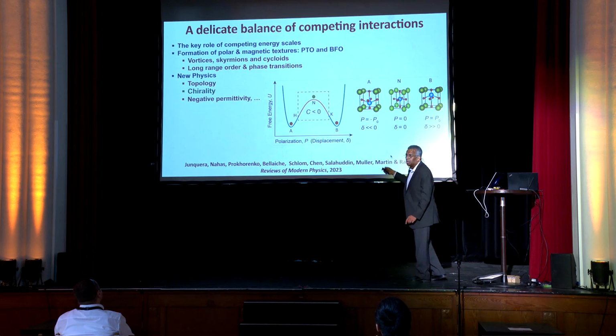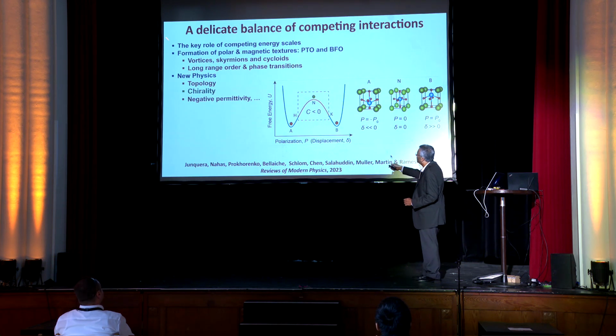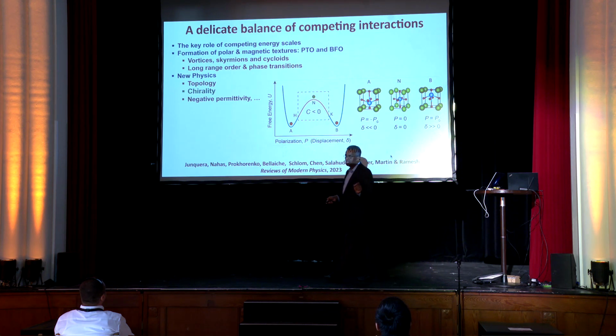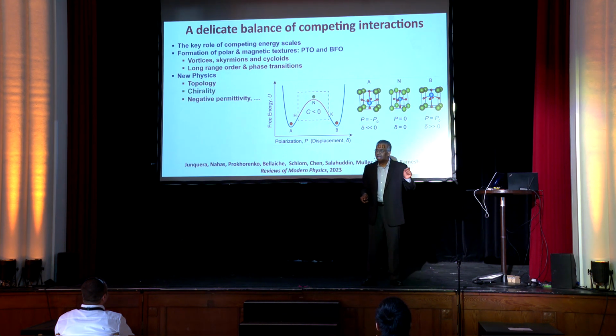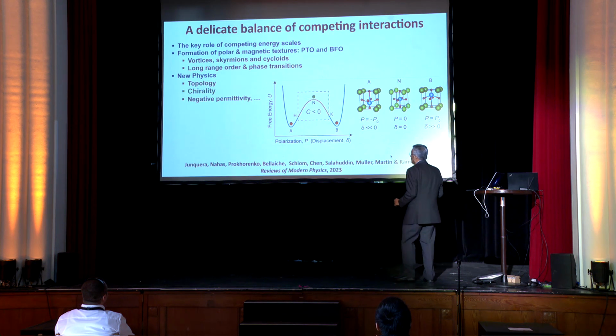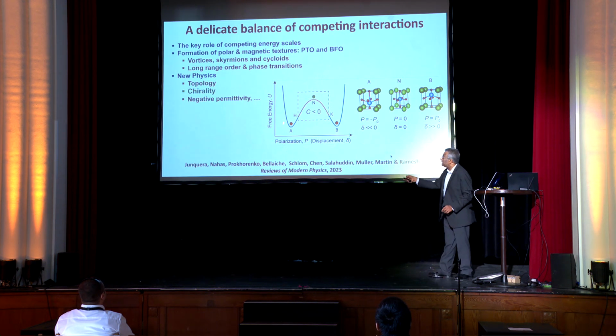So what we're going to do is to use epitaxy to create competing energy scales. And that leads to the formation of both vortices and skyrmions. These are not magnetic skyrmions, so the origin is slightly different. Unlike in magnetism, in ferroelectrics, the lattice plays a very strong role. In most magnets, it does not play a big role. And it leads to a lot of very interesting new things, which I'll show you in just a second.